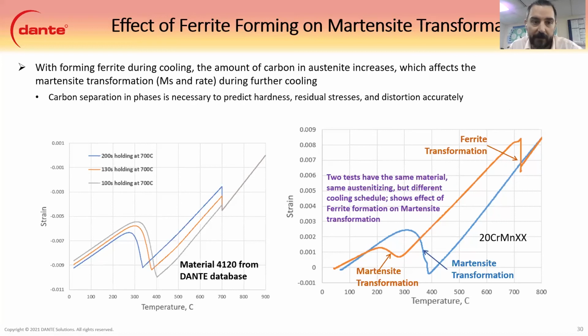And you can see the effect on martensite transformation, the martensite start right after that. Whereas as you hold it for 200 seconds at ferrite, the MS is now down to almost 325 or 330. Whereas if we held for only 100 seconds, the martensite start is at 400 degrees. It's a big difference, and that's why we added it to the DANTE model in order to account for that.